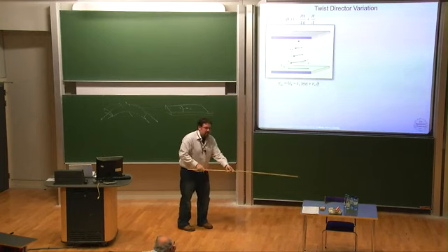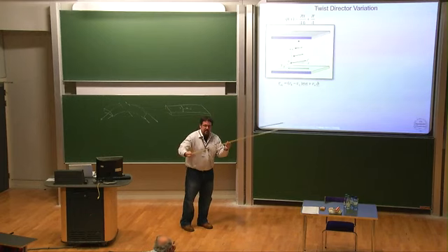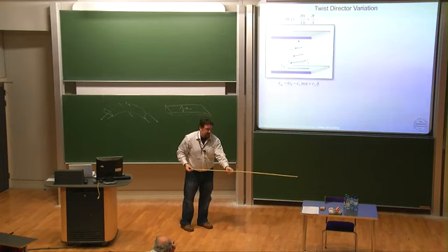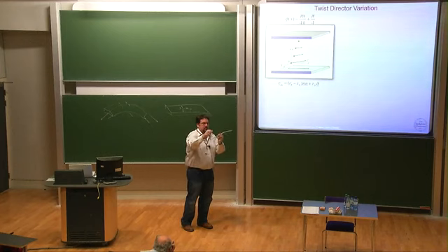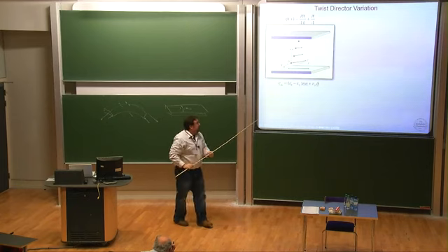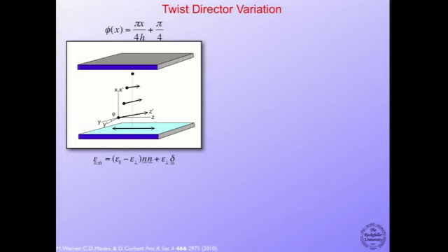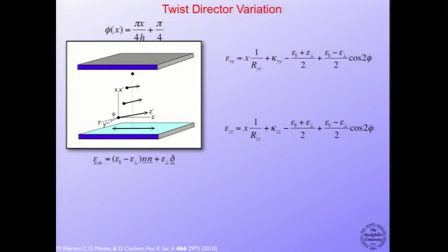So another way, instead of doing this to get that, you could have done this. You could have twisted through the thickness. By twisting, if you're heating it, you're shrinking along the director here, and now you're extending along the director on the top. So again, this is the geometry. You start along the long direction, you end up normal to the long direction, and you do the exact same thing. Again, we set up the simple linear elasticity bending equations, and you turn the crank.